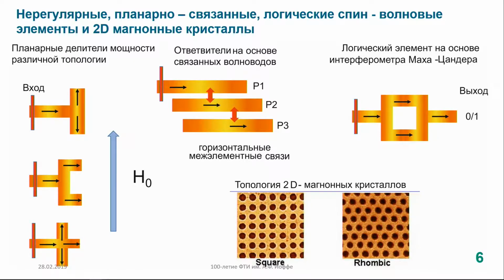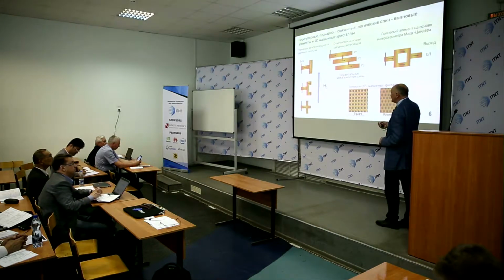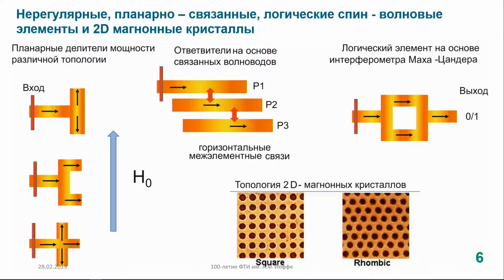And depending on geometrical sizes and external magnetic field, there are different types of waves which can propagate in the material. For example, if you have such a film and the magnetic field lies perpendicular, say, to this first part, this is the excitation antenna. In this case, in these parts of the film, we excite so-called surface magnetostatic or surface spin waves. And their frequency is different from the frequency of the wave which propagates in this direction. Therefore, it is in principle impossible to excite, with the same frequency, waves for a particular external field in this part of the film or in this part of the film.